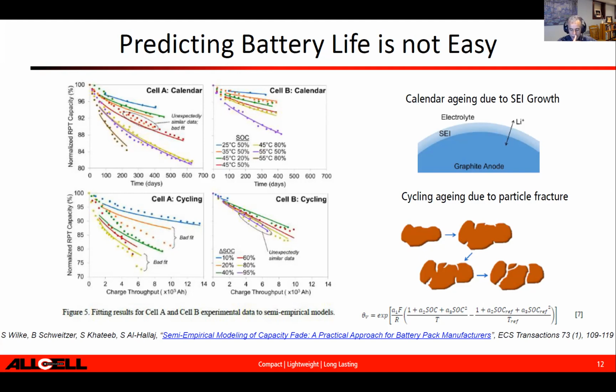What we found is that the major challenge with calendar aging and even some performance is due to what's called the SEI layer growth, which is the solid electrolyte interface between the electrode material and the electrolyte. And as the temperature increases, you start growing that layer by depositing more material, and that adds to the impedance growth. In some cases, we also found that upon aging, one of the failure modes is basically the fracture of the particles that leads to a sudden or gradual drop of battery performance.